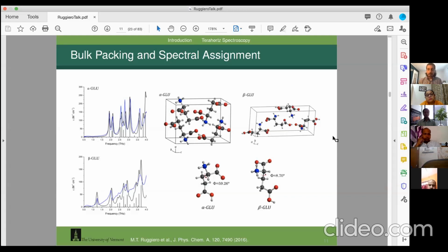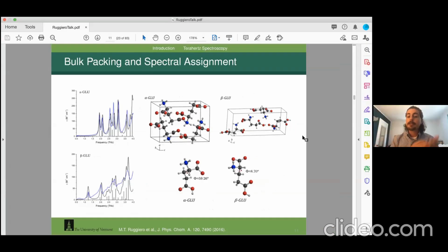And that's really important. And that's really useful because you can use terahertz spectroscopy as a complement to X-ray diffraction. And what's nice is X-ray diffraction may take you a half hour per measurement, whereas terahertz, we acquire data at 15 hertz. So I can get 15 waveforms measured in a second. And so that's really nice. So it's really fast. We don't have to grind the sample too much or anything. We can get really nice data. But it also leads to its biggest problem. The biggest problem with this technique.